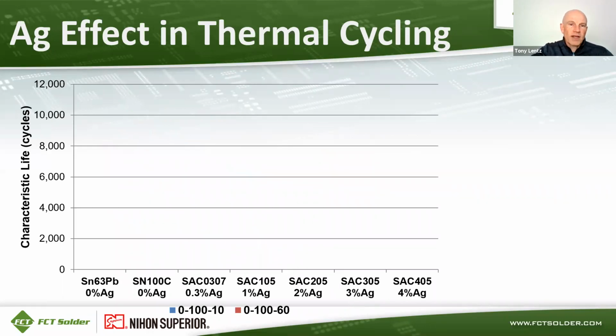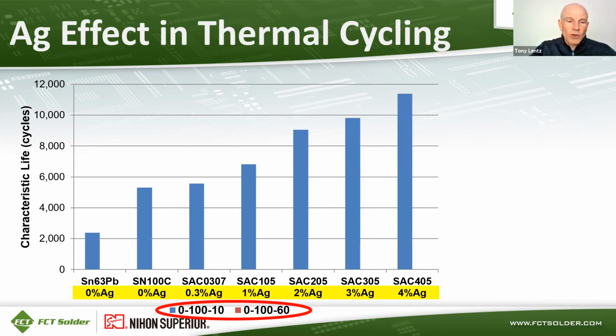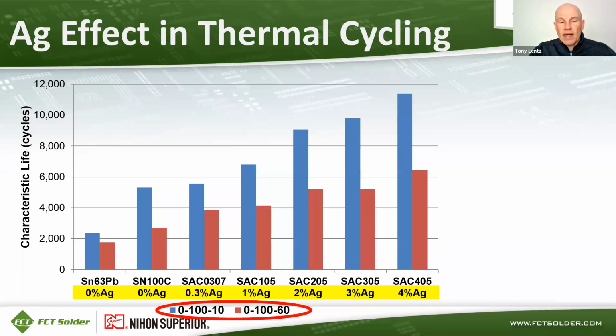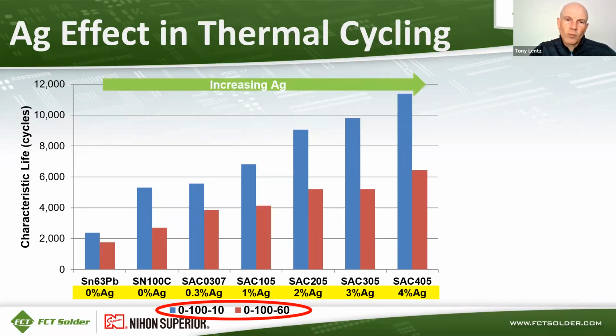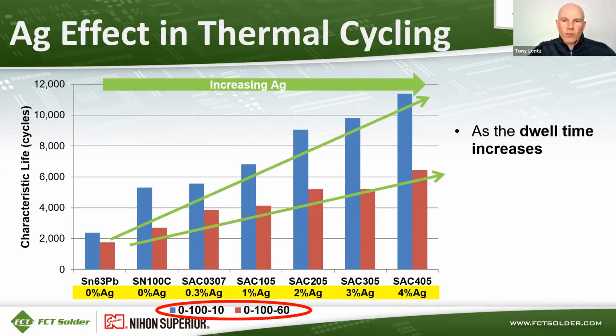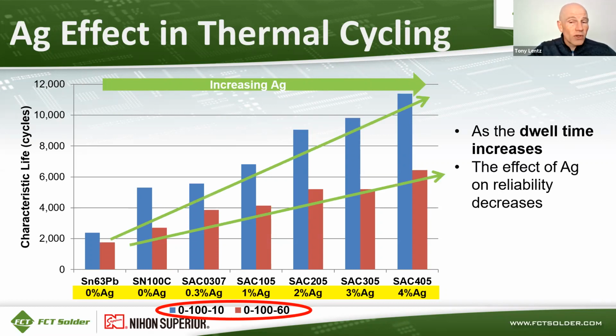Here's some more data for silver effects in thermal cycling, characteristic life on the y-axis, and different solder alloys. From left to right, silver is increasing in concentration on the x-axis. And we're running two different temperature cycles here. There's a 0 to 100 for 10-minute dwells and 0 to 100 for 60-minute dwells. So the first set of data with the blue bars is the 0 to 100 with 10-minute dwell times. You can see an increase in characteristic life as you go up in silver concentration in the solder alloy. If you go to 60-minute dwells, that increase in characteristic life is much less. These data points are much closer together in the red bars. So that shows that as the dwell time increases, the effect of silver on reliability decreases.